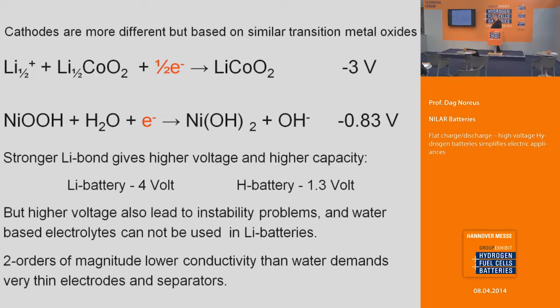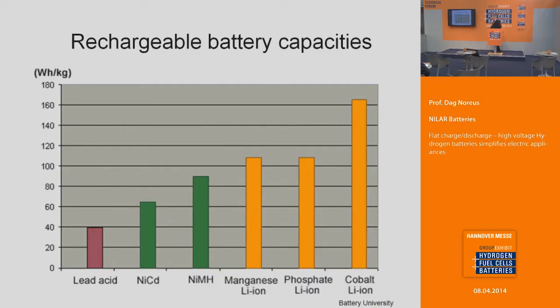And one big advantage with a hydrogen battery is that you can use a water-based electrolyte. This has two orders of magnitude higher conductivity. And this also makes it easier to make thicker electrodes, a more robust battery. In a lithium battery you need very thin electrodes and very thin separators and very high quality, and this drives cost up. So in the end there's not so big a difference between the storage capacity of the different batteries. Best is of course the cobalt-containing, then you have the phosphate and the manganese, but the metal hydride battery, or what we call the hydrogen battery, is not so far away.